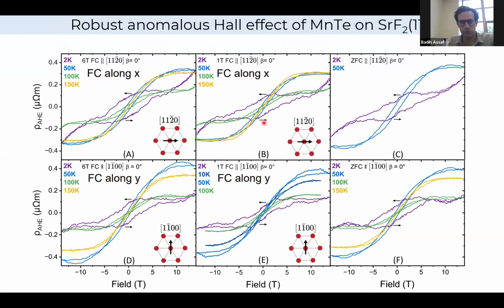Conversely, when we have MnTe grown on strontium fluoride, the data set that I showed you earlier, the field cooling doesn't have an impact. Even if we don't field cool, even if we cool down under zero magnetic field, we do observe a spontaneous anomalous Hall effect. And then field cooling does not impact the quantitative details of this anomalous Hall effect significantly. So this anomalous Hall effect is unique to MnTe grown on strontium fluoride. And we believe it's related to the properties of those films.